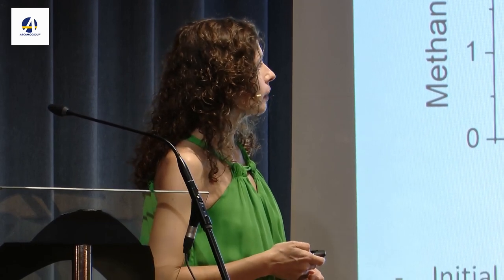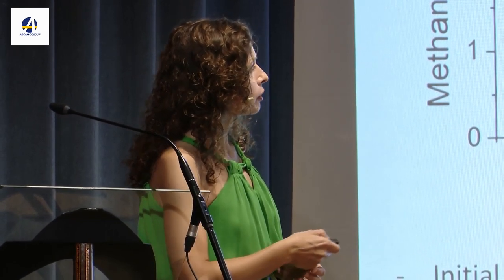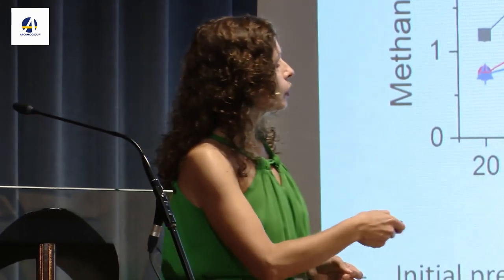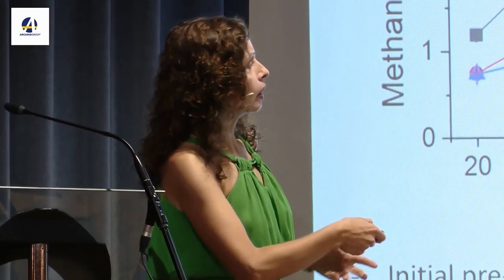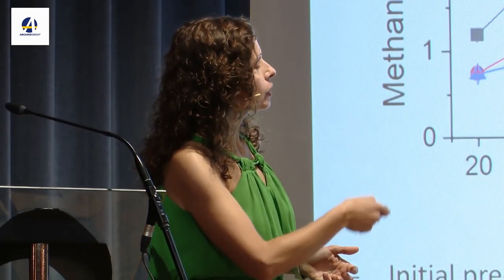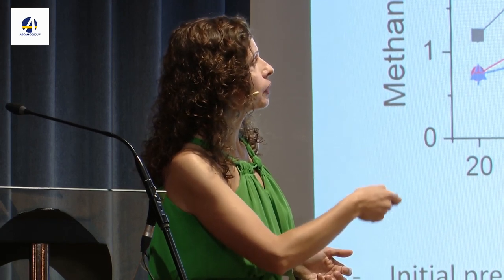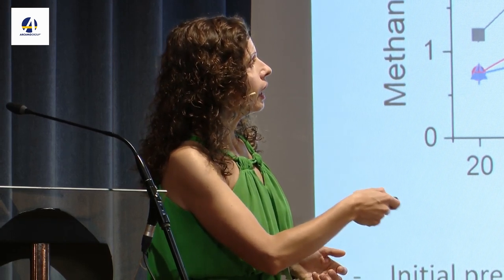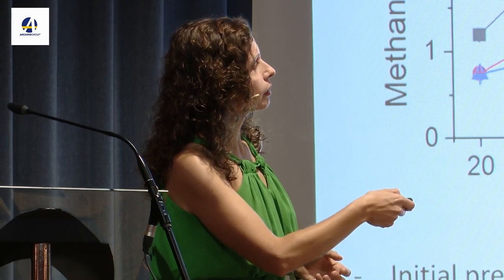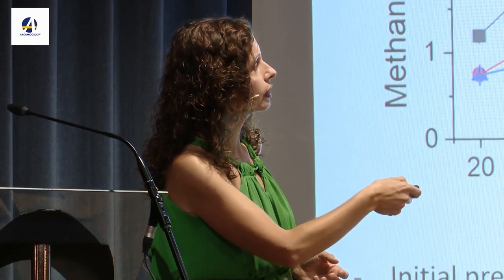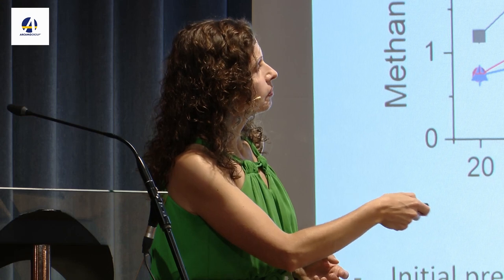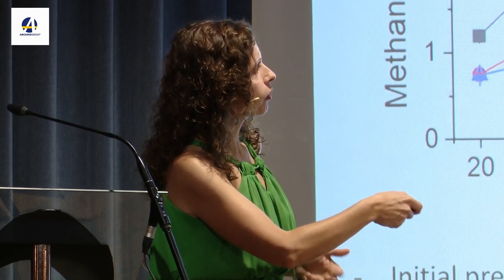And we can also follow with our spectroscopy and microscopy data what is the performance of these materials. So if you start with your precatalyst, looks like this. This is how it will be at low temperature. Once we start the reaction, it starts to reshape. You get something more like this. And then I will demonstrate in a minute that under reaction conditions, you get an overlay of zinc oxide. And this is still very good performance and stable.